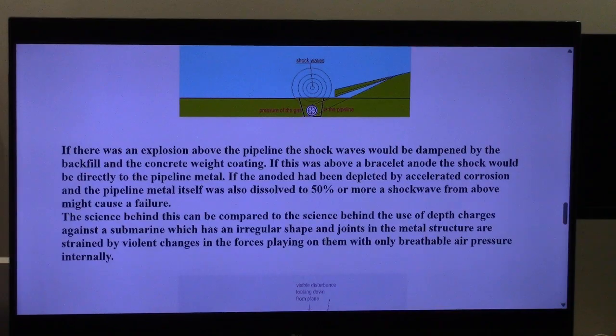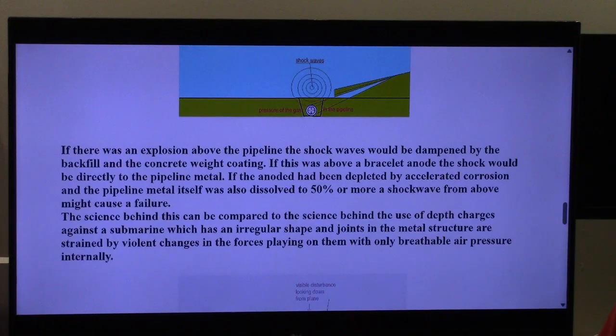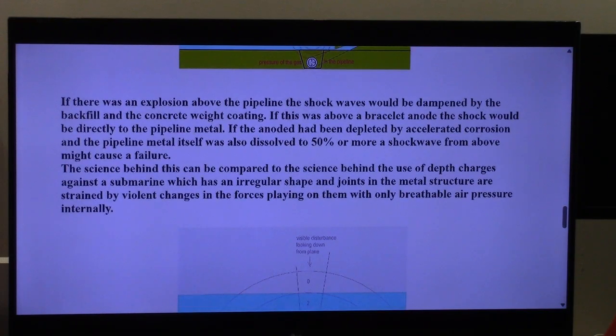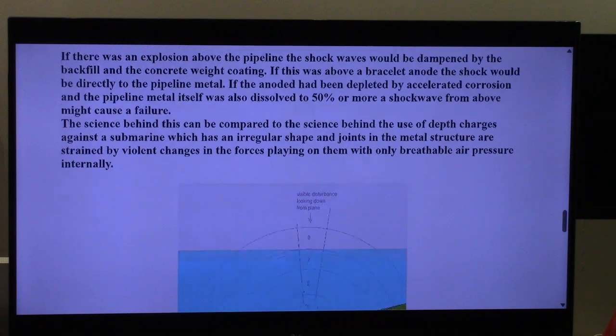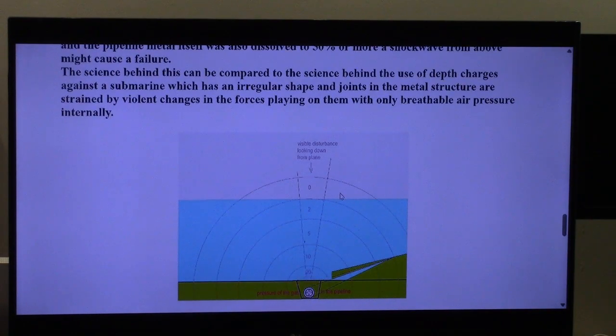if the pipe anode had been depleted by accelerated corrosion and the pipe metal itself was also dissolved to 50% or more, a shock wave from above might cause failure. The science behind this can be compared to the science behind the use of depth charges against a submarine, which has an irregular shape, and the joints in the metal structure are strained by violent changes in the forces playing on them, with only breathable air pressure internally.